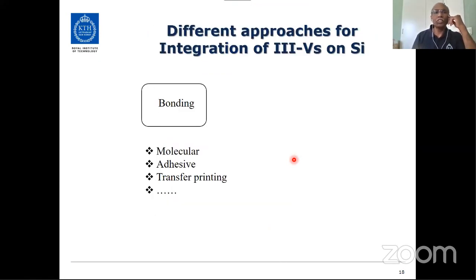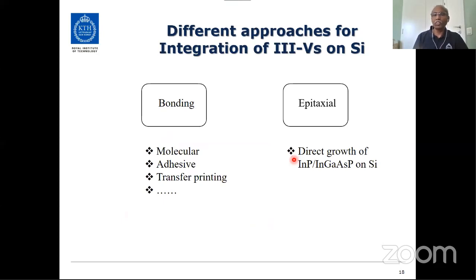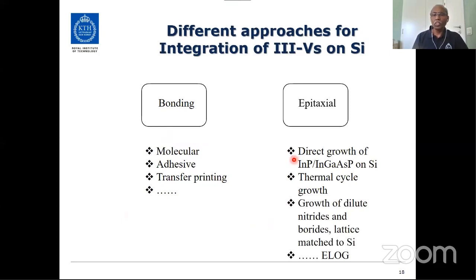So there are different approaches for integration of III-Vs on silicon. One is the bonding approach. There are several approaches in bonding: molecular, adhesive, transfer printing, and epitaxial methods: direct growth of indium phosphide, indium gallium arsenide phosphide on silicon, thermal cycle growth, and growth of dilute nitrides and borides lattice matched to silicon, and epitaxial lateral overgrowth. People are taking several approaches, and we are trying to do this integration through ELOG, what we call ELOG, epitaxial lateral overgrowth.